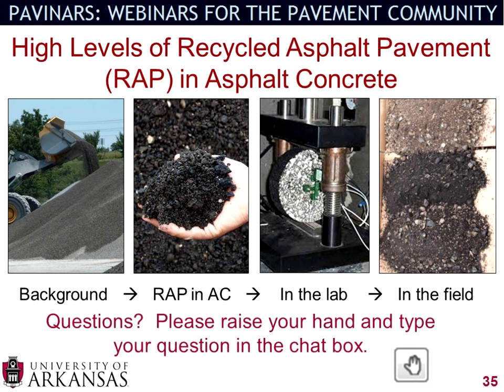And this is an excellent question, Matt, and I think it's a function of how much crack seal material is actually being pulled up. So if you look at some roads, you got crack sealing every foot, every 2 feet. I think then you will start to see a pretty significant effect of that crack sealing mixture in the RAP materials. Now, if you're only sealing every 20 feet or something, it'll probably kind of come out in the wash and you really won't notice that.